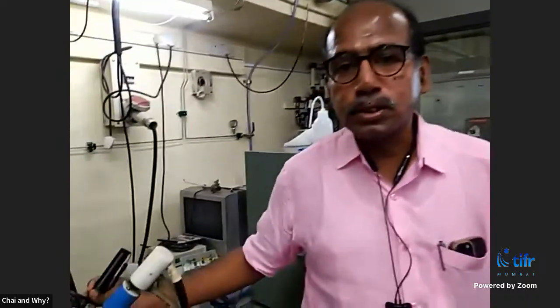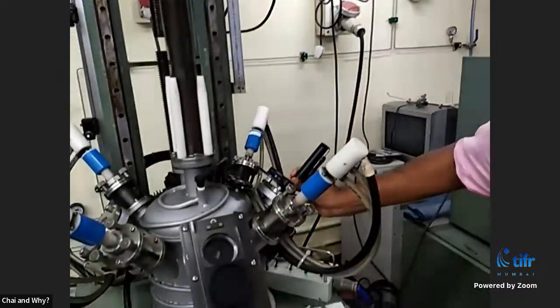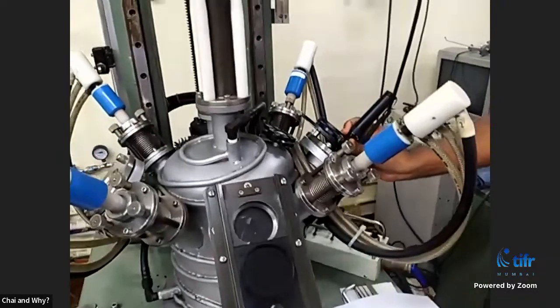So would it also mean that it's difficult to melt copper in this furnace? Yes. Melting copper in this furnace is relatively difficult because the copper hearth is water cooled, and whatever electric arc is hit on the copper material will be transferred to the water because of the high thermal conductivity of copper. So let's see how this sample is being melted right now.